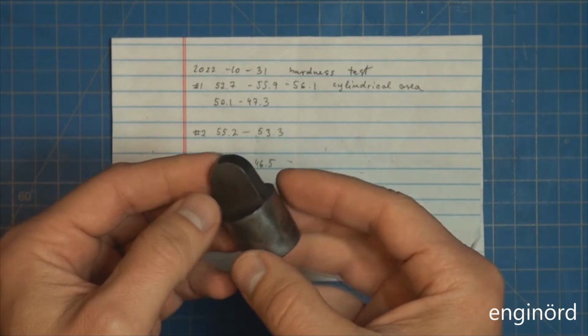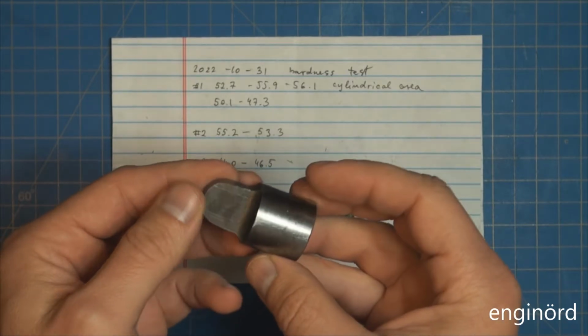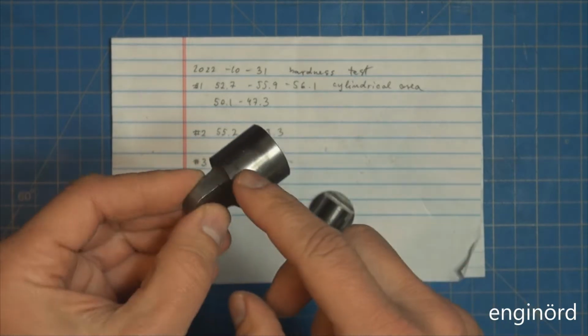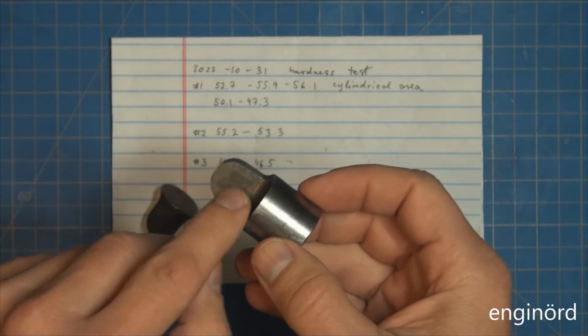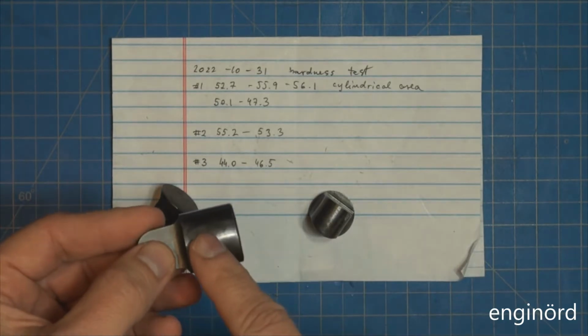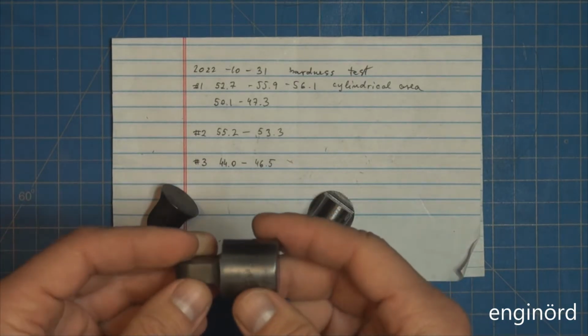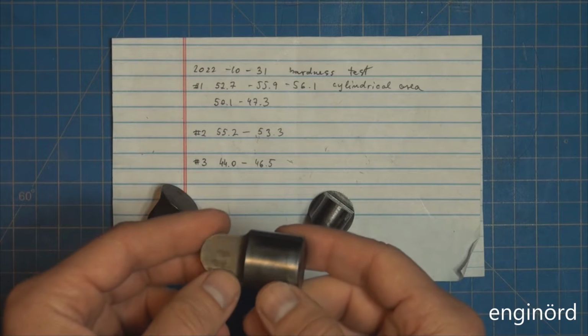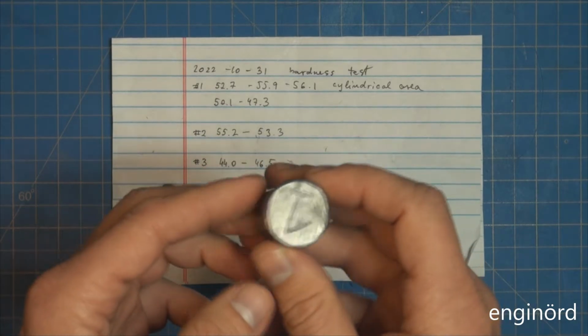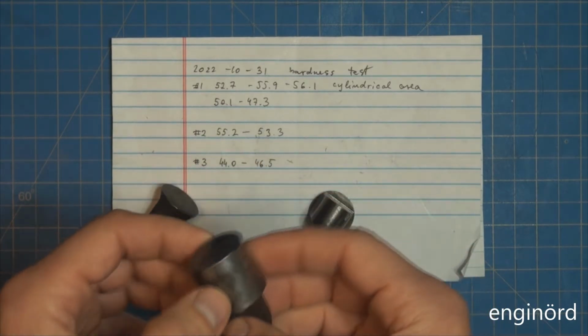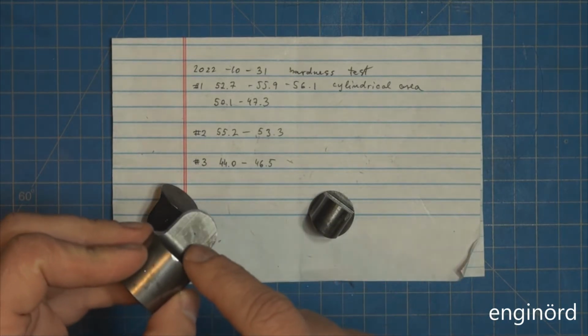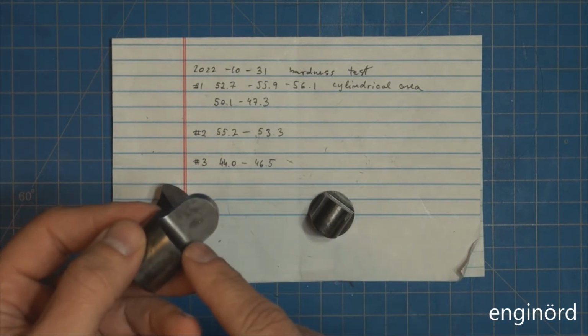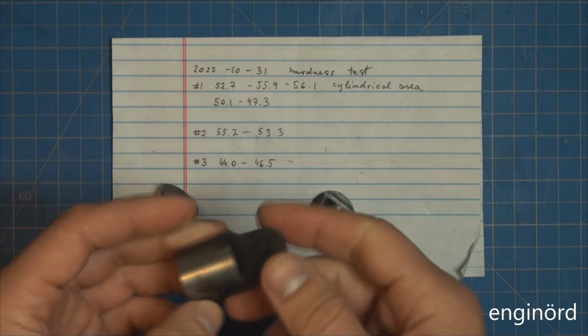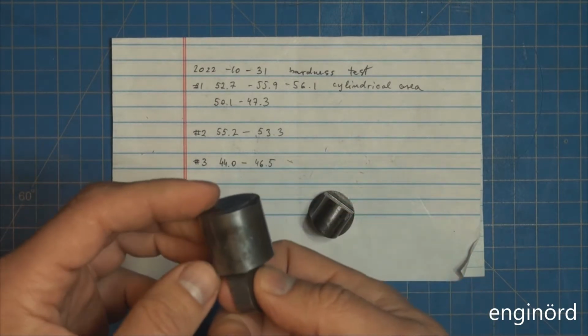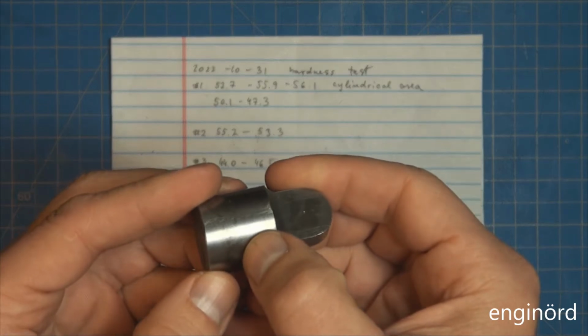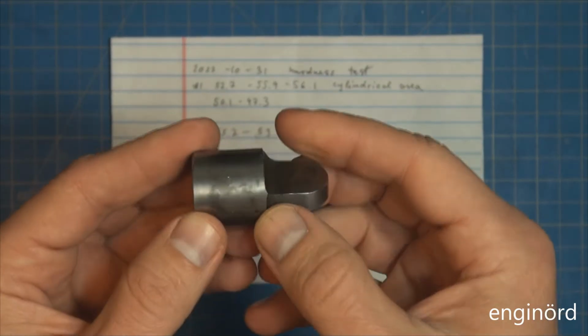The surfaces seem okay. I did a hardness measurement both on the cylindrical area and on these flat surfaces. So on sample number 1, it was 52.7, 55.9, 56.1 on the cylindrical area, and then on the flat surfaces 50.1, 47.3. You can see the little divots here where the hardness tester hit it.